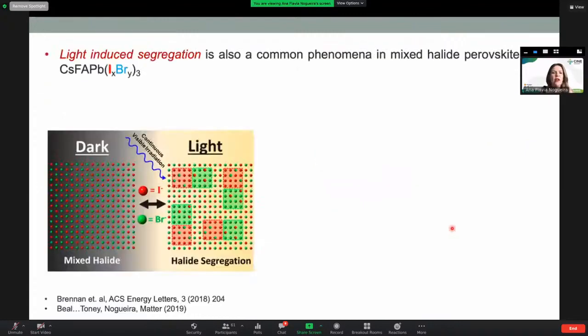There is another problem in terms of degradation. I'm not sure I can call it degradation, but it is the light-induced segregation. We use different compositions of iodide and bromide because this is really important to adjust the band gap, as we want to go for the most ideal band gap in order to absorb most of the light. So most perovskites, although they have many different cations in the A site, have different ratios between iodide and bromide. But there is a problem.